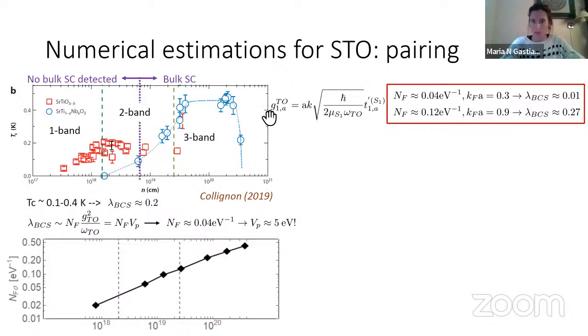We get the expression for G. We get the estimate from ab initio for this induced hopping. We place here the experimentally measured frequency of the mode. And then I have that my lambda BCS is the density of states times U squared divided by the frequency. So I get two numbers in two different regimes. One is for this very low density of states, which gives me an extremely small lambda BCS. So in principle, this mechanism in this low density of states cannot support superconductivity on its own, not with this number. Remember that it has to be of the order of 0.1, 0.2, 0.3.